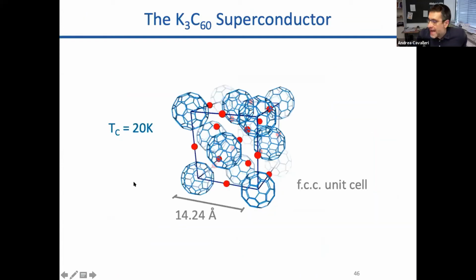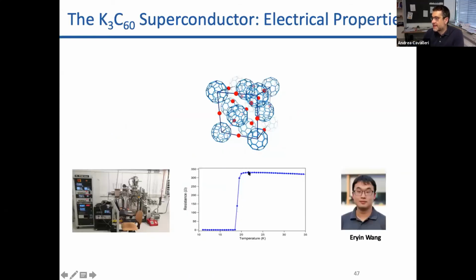So I will tell you now a little more about the physics of this specific material that we chose. This is the potassium-doped K3C60 superconductor. You should think about this material as an FCC lattice of C60 molecules, which have been electron doped 3 times by the presence of the alkali atoms. So you should think about an FCC lattice of C60 3- molecules. And this is a material that exhibits superconductivity at approximately 20 Kelvin.